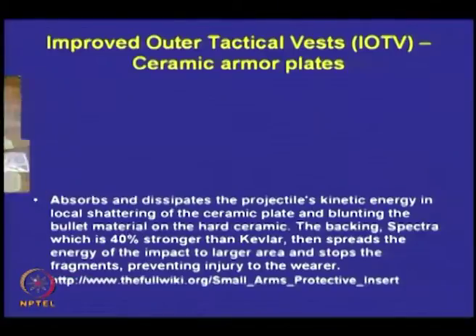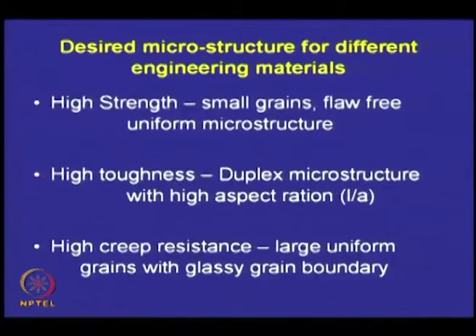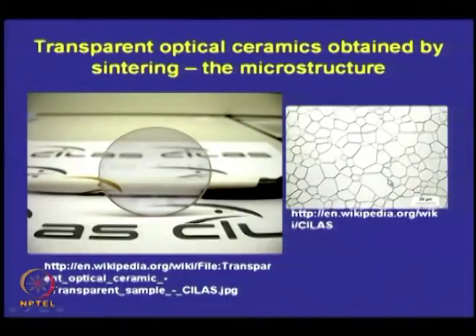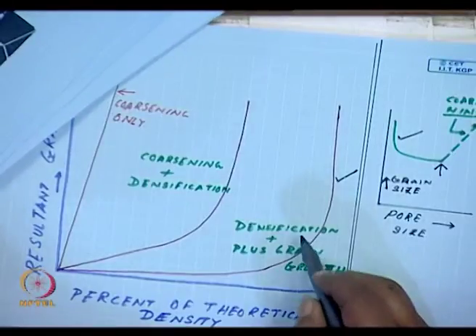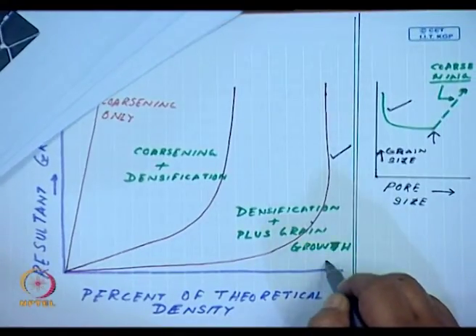In solid state sintering, what I require is this particular type of microstructure, while I shall always try to avoid the ones with porosity. To have good control over sintering, what we require is, going back to my original graph, densification followed by grain growth.